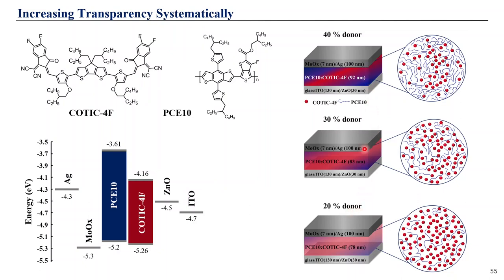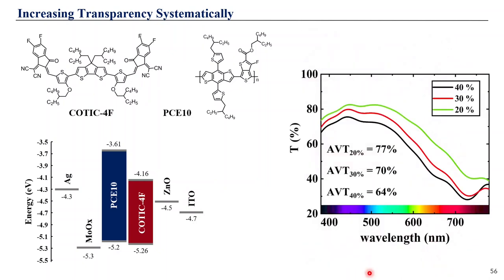Also we were reducing the active layer thickness. This played some important role, which we will discuss a bit later. So we definitely achieved higher average visible transmittance by diluting donor concentration, reaching up to 77% for the bulk heterojunction active layer, which is the record parameter among reported values.